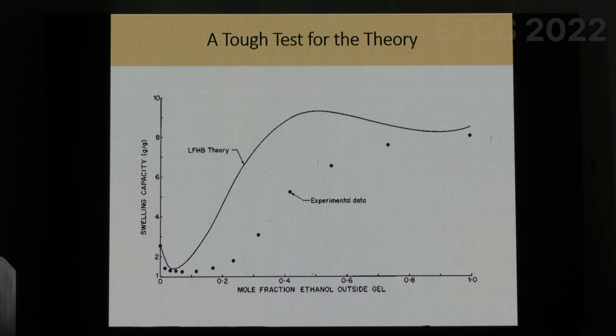And so if my theory can predict this even qualitatively, then this is like a real hard test for the theory. And lo and behold, the theory does do a great job of it, and there are no fitting parameters here. This is pure prediction. It's not quantitative, but it captures the difficult re-entrant phase transition.